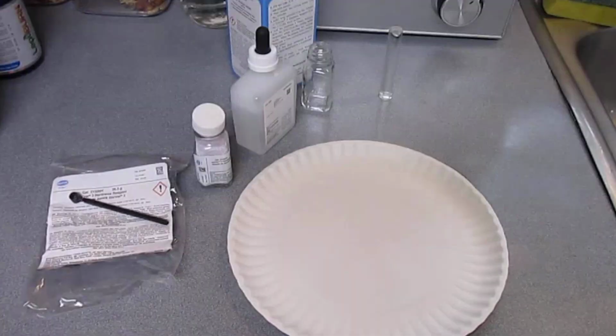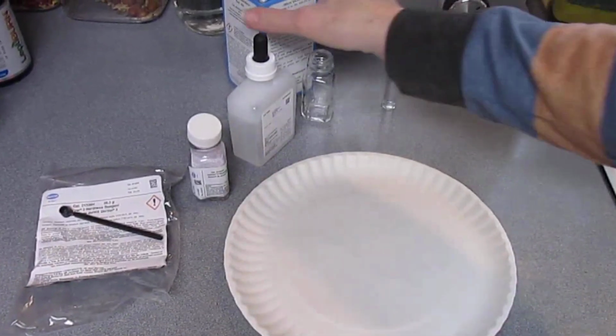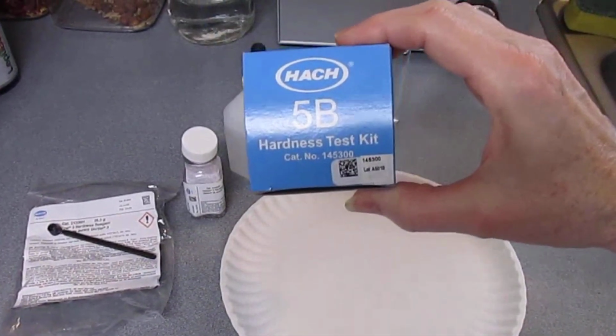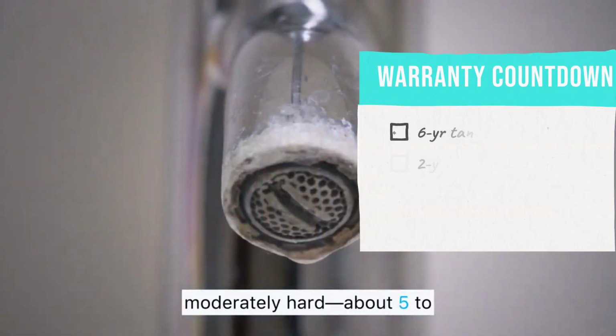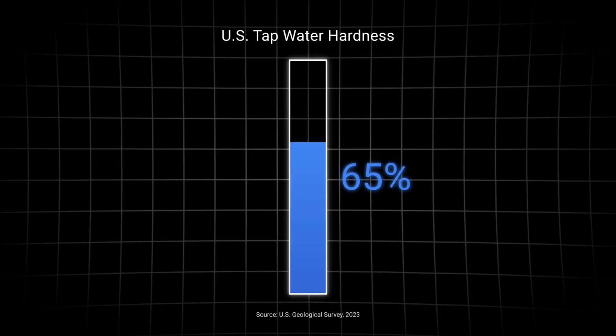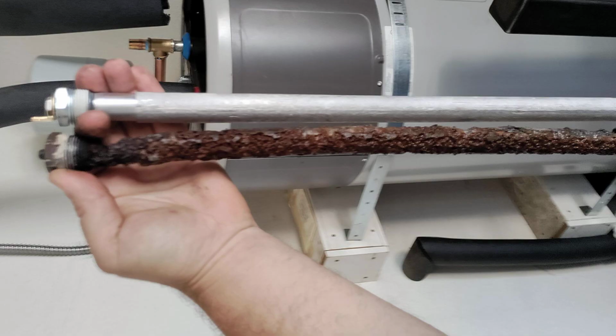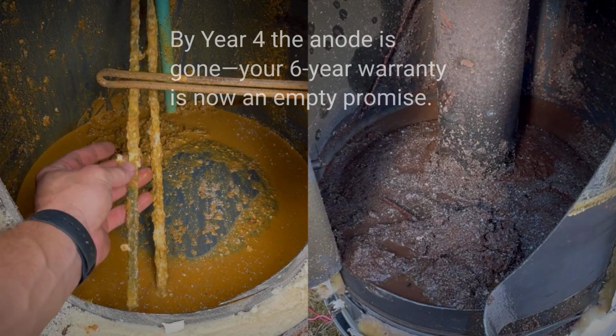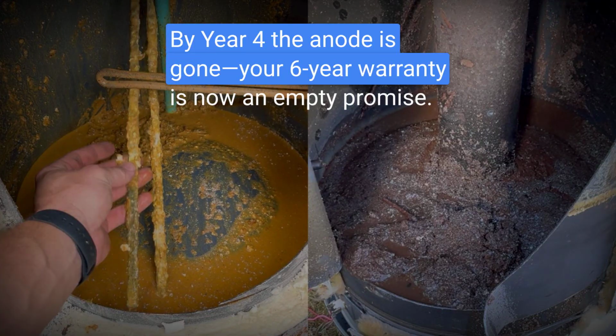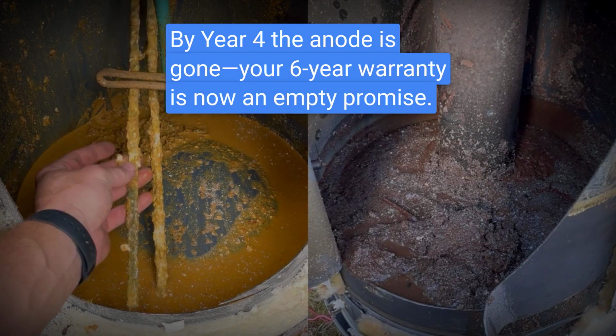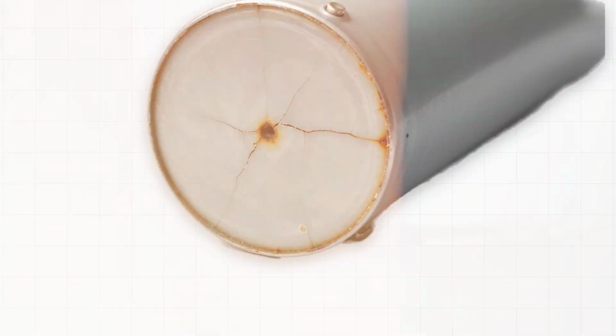Municipal water reports put the national median hardness at about 110 parts per million, or 6.4 grains per gallon. 65% of Americans get water classified as moderate or hard. In these conditions, the anode depletion rate outpaces the manufacturer's coverage. By the 4th year, most tanks have lost their only real protection against galvanic corrosion. From that moment, the glass lining, vitreous enamel, faces daily attack.